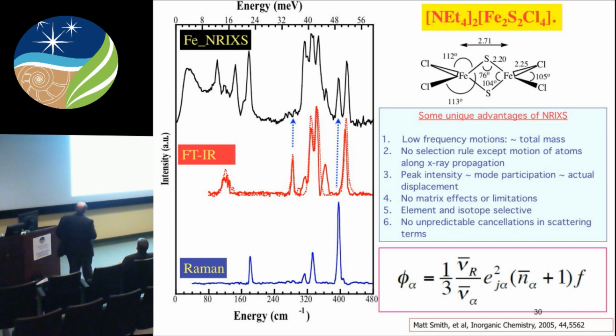So for a spectrum like this, we encourage people to use enriched iron, so 57 enriched. A good spectrum like this in a protein, for example, if you have an enzyme, it may take a day. If you have pure iron, it may take maybe an hour or less. Right? So it pretty much depends on the geometry. If you're in a diamond anvil cell with 1% iron in FeO MgO, that may take a day. But if you are measuring an iron-rich sample, a few hours is enough. But definitely, this is not a very fast technique.